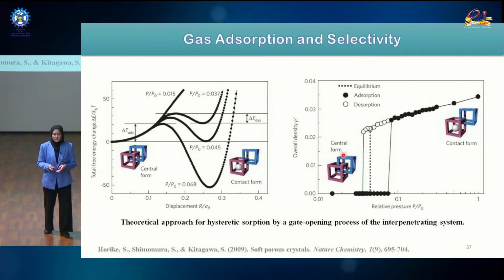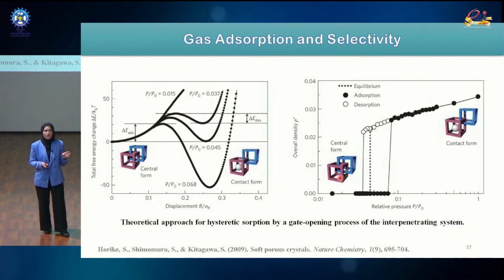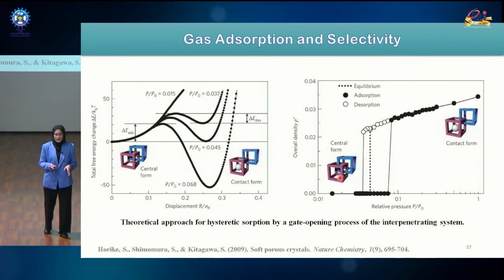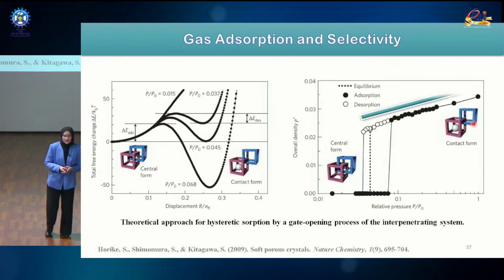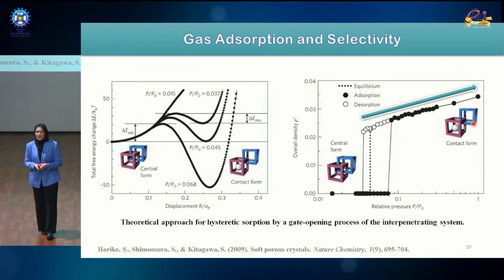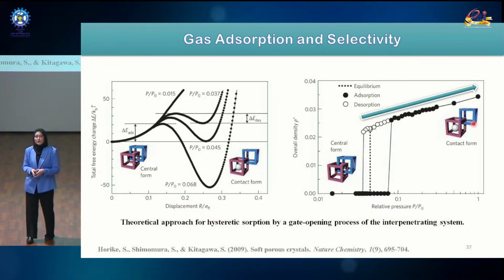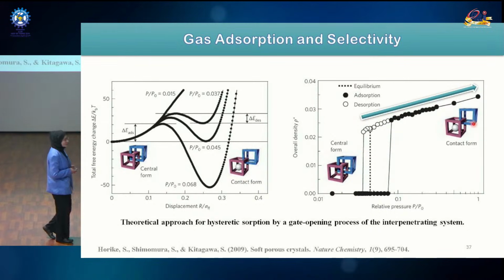At low pressure, the framework stays closed, so only a little gas enters it. But once a threshold is reached, the pore opens up and the MOF takes in a large amount of methanol at once. This sharp jump is what we call gate opening behavior, and it shows how soft porous MOF crystals can selectively adsorb different gases depending upon the size and interaction. And this is what makes these useful for smart separation and controlled uptake.